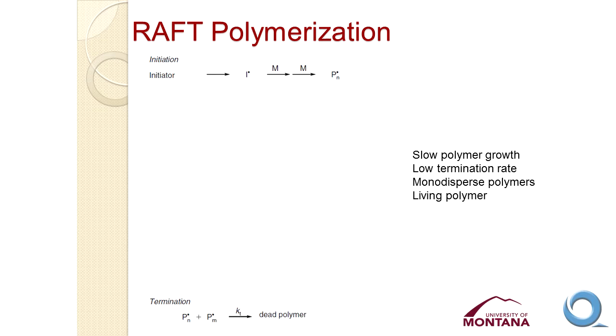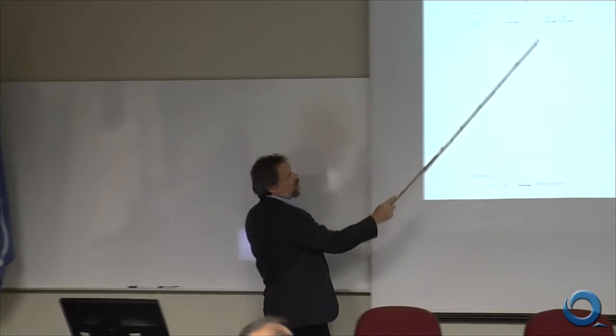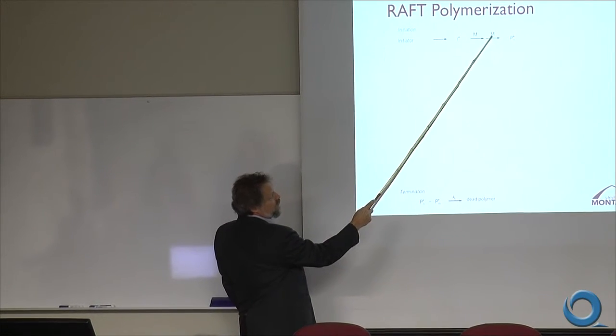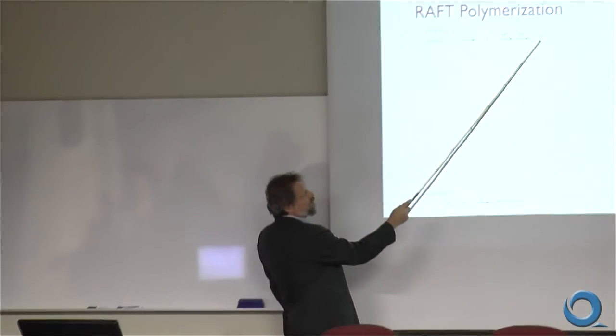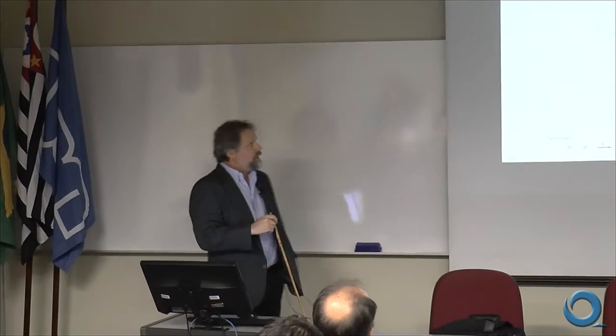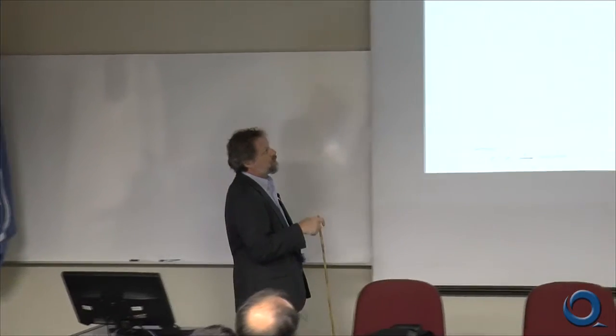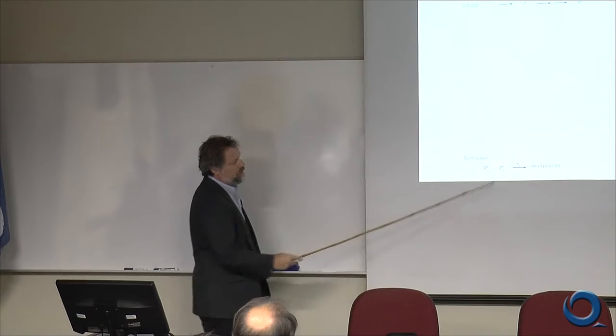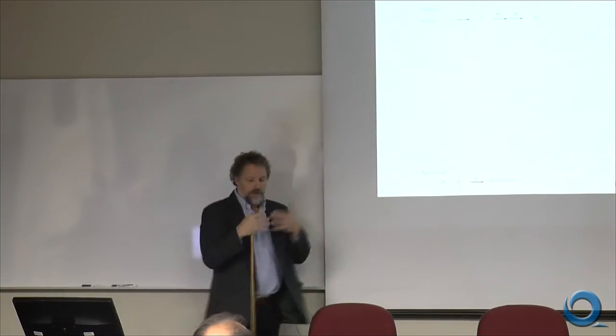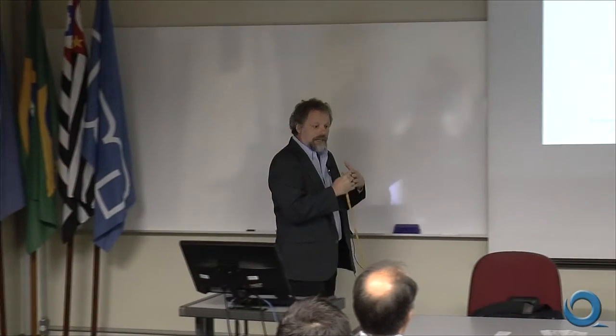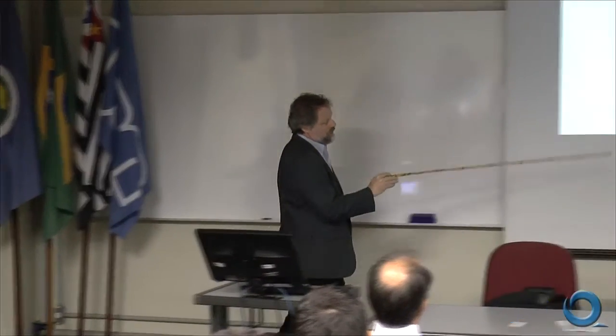So we start with a monomer and an initiator. We initiate the polymerization by the reaction of that free radical initiator with the monomer, and then that free radical will react with another monomer to form a growing polymer chain, which is an active free radical in solution. And this process continues and goes on quite rapidly because free radicals, as you know, are very reactive. And the process is terminated when two of these growing free radical chains find each other in solution and react to stop the polymerization. What you end up with then is a polymer chain which is no longer a free radical and can no longer be initiated. You can't initiate it in a second process to continue the polymerization. So we call it a dead polymer.